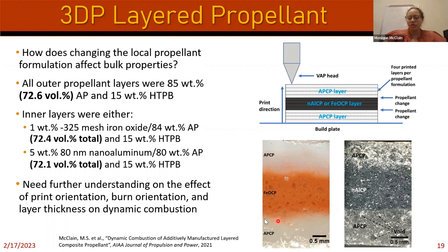We can see there's a little bit of intermixing here between the layers, but considering overall that this is relatively thin, right? It's only about 3 millimeters thick. This intermixing is not terribly bad for our first attempt. And honestly, I think it could improve if it was a more viscous mixture, there would probably be less mixing at this interface. And then here I have an example of the other type of propellant mixture. Again, we still have ammonium perchlorate on the edges here, but then in the middle, we have that nano aluminum mixture.